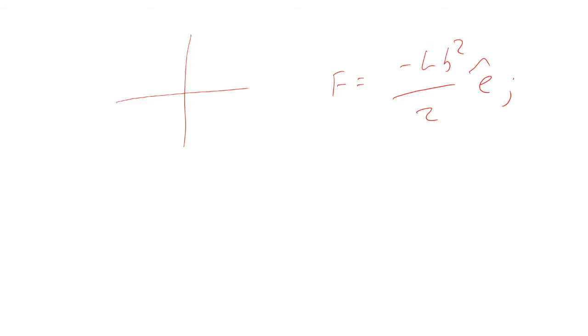I specifically say that total force. So how do you do it? You would plug this into the Peach-Koehler equation, and that would give you force as a function of position. Then you find the total force by integrating along the line length from negative infinity to positive infinity.